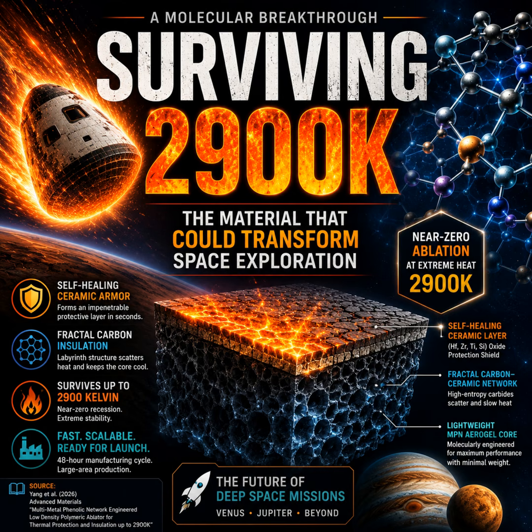But a perfectly uniform aerogel sitting on a desk at room temperature doesn't solve the re-entry problem. Right, because it still has to survive the fire. Exactly. The true test of this MPN material is what happens when it's blasted with a 2900 Kelvin oxyacetylene blowtorch. Wait, 2900 Kelvin. That is hotter than molten lava. Much hotter. Under those conditions, a standard polymer aerogel instantly vaporizes. Just poof, gone.